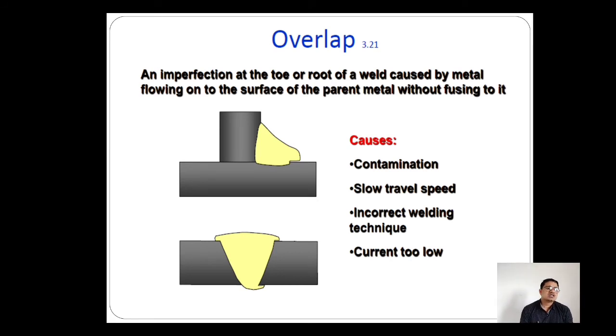So you can see the causes. Number one cause shown is contamination. If any oil, liquid, grease or any kind of dust, dirt, or corrosion is present, then it may happen. The second one is slow travel speed. At the time of slow travel speed, the current is going high, and the liquid metal is flowing, not melting the parent metal. The third one is incorrect welding technique. Once we are not using the correct welding technique, then it may happen. The last one is the current being too low. When current is too low, it means only the electrode is melting, not the parent metal. Then such kind of discontinuity may show.